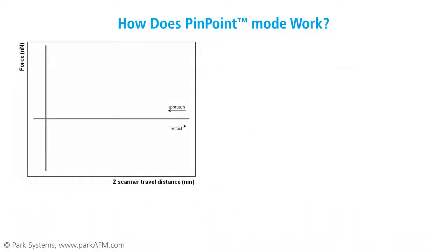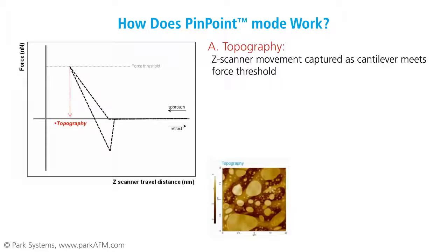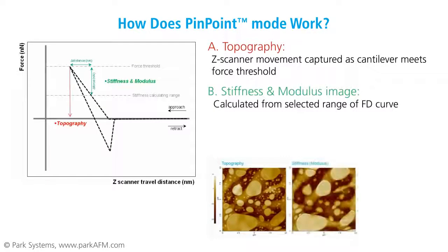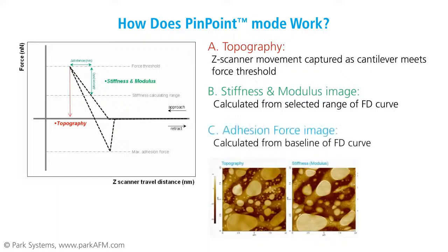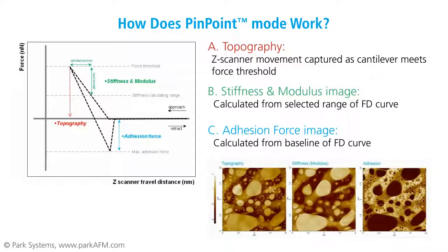From a single data point in PinPoint mode, stiffness, modulus, and adhesion force can be determined by an automatic calculation process in the system. After the topographic data is collected, stiffness and modulus can be calculated using a selected range of the force distance curve. Applying this data to the Hertz formula, the elastic modulus can be calculated. Finally, the adhesion force can be acquired after calculating the maximum from the baseline of the force distance curve. In PinPoint mode, these data points are collected for each pixel in the imaging area and displayed as an image. The final result is a quantitative mechanical property distribution image of the multi-component polymer.